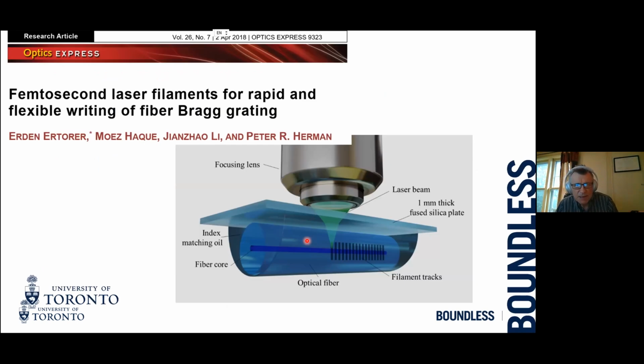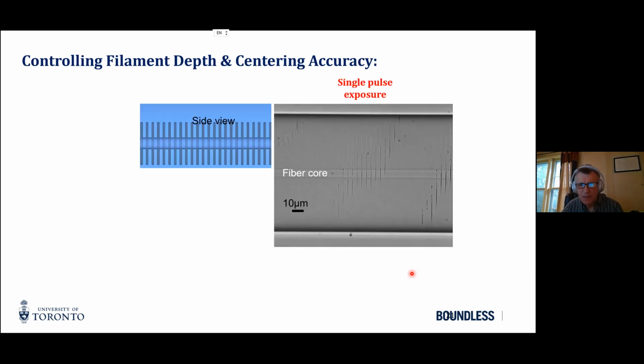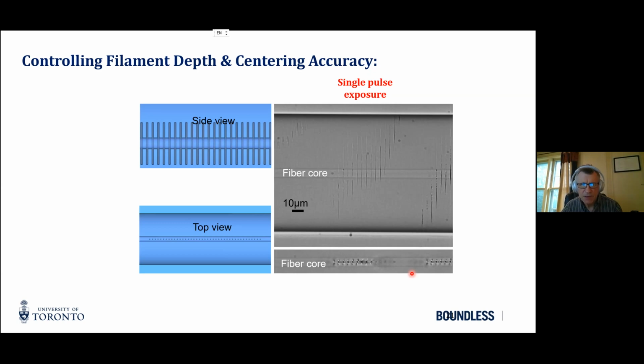So we've played with and tried to perfect writing these in different ways. Here is a filament lined up on Bragg spacings with this cartoon, and it's kind of tricky to build this. Here we're using a glass plate. We're actually using the aberration of the first surface to lengthen the filament, as we showed you. Then we're using refractive index oils to compensate for an aberration here, which would destroy the filament symmetry, and this would stop working. And when you line these all up, you can in fact get these filaments at controlled positions inside the fiber. We have about 1 micron positioning control, and we can get very uniform periods.